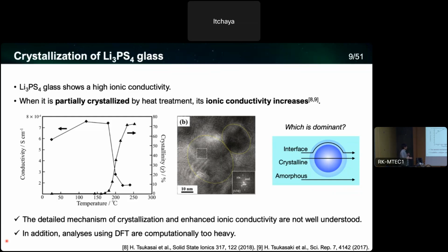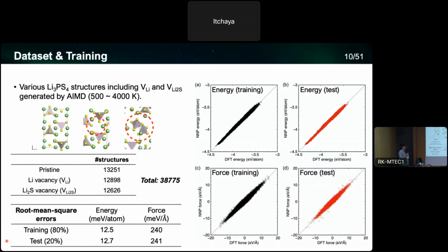But the problem is the density functional theory calculations are too heavy when we want to deal with this kind of model. So we applied the neural network potential to these target materials. So what we need to do first is the training dataset preparation. I will just briefly go through this slide, but we prepared a lot of different atomic configurations using ab initio molecular dynamics simulations. We set different temperatures from lower to quite high, around 4,000 Kelvin, and we generated various structures, from the ones close to the crystalline to quite distorted structures.